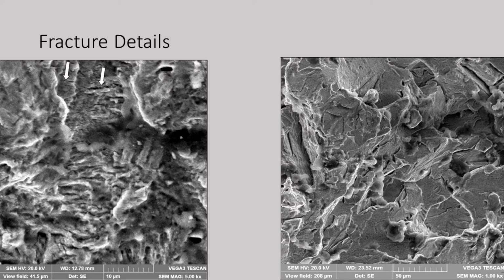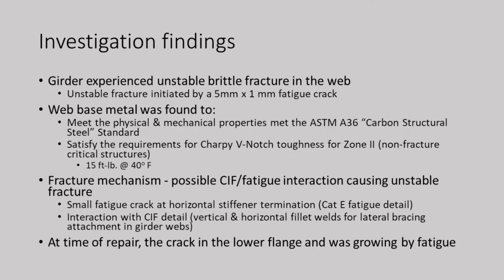It's where cracks ran across grains. You can see maybe the outline of the grains here. They didn't deform, they just sheared. They broke, they pulled apart. They didn't shear, they just separated. These are low energy fractures, and that's why you get so much crack propagation with unstable brittle fractures. So what were our investigation findings?